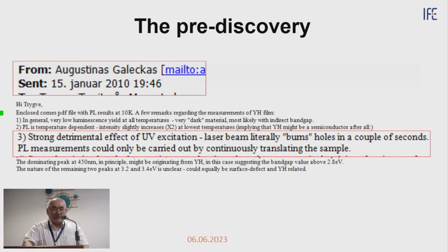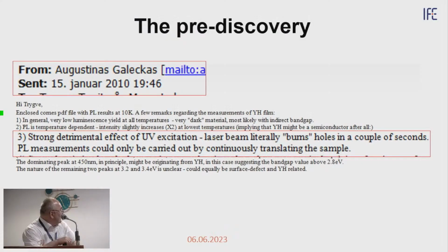Yes. So here I would like to say a little bit about the history of the discovery of this material. My PhD student, Trygve Mongstad, was studying new materials for silicon-based solar cells. We deposited aluminum hydride, magnesium hydride. We wanted to bring new materials for silicon-based solar cells. As such, we were interested in materials that contain a lot of hydrogen, because hydrogen passivates a lot of detrimental impurities in silicon, like deep level impurities, transition metal impurities. So our idea was, why not use metal hydrides? Because there are so many hydrides, even if just 0.01% of hydrogen diffuses and passivates those defects, then all would be okay.